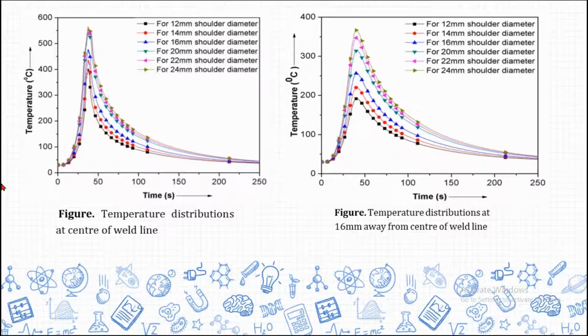And we tabulated all these values on some graphs, like heat distribution at the center of the welding for 12 mm, 14 mm till 24 mm. This is the maximum temperatures obtained at the center of the welding. And this plot shows the temperature 16 millimeters away from the center of the welding for all the different tool shoulder diameters.